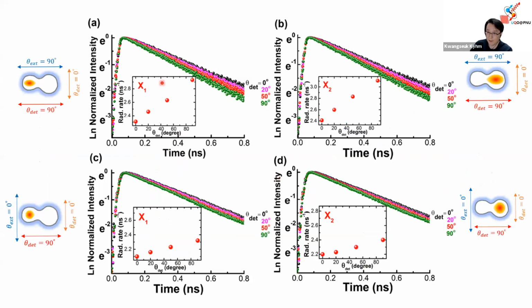And time resolved again. So if the wave function extent or size is large in this scale, the oscillator strength is large, therefore the decay time will be very fast, or the decay rate will be very large. So 90-degree, for example, here, decay rate is large. Yeah, although it's time resolved PL, we assume it represents the radiative decay rate, and it increases in such a way for X1 and also X2 here.